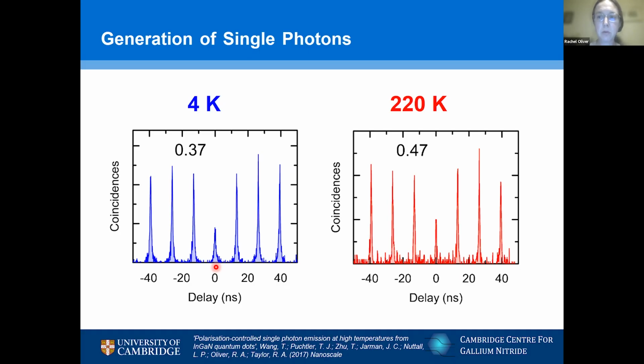Quite often when people do this type of analysis, they use a subtraction technique to remove that background and say, oh, look, we have beautiful single photon emission from our quantum dot. I generally try not to do that because, yeah, okay, the quantum dot may be a single photon emitter, but if you can't make a device where you eliminate the other photons from other sources, then the fact that you can use a kind of mathematical trick to get rid of those excess counts in your trace is not really all that interesting. So yeah, I'm very pleased with this device, when I grew it anyway, that it operates up to these fairly high temperatures accessible by Peltier cooling, which might be quite useful in practical applications, but it does have an issue with this background emission.